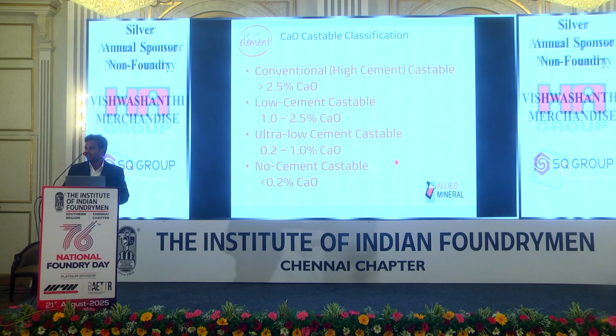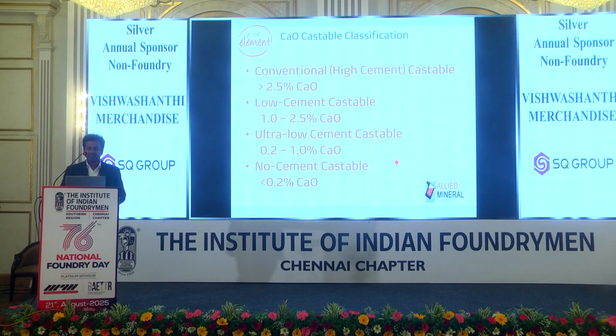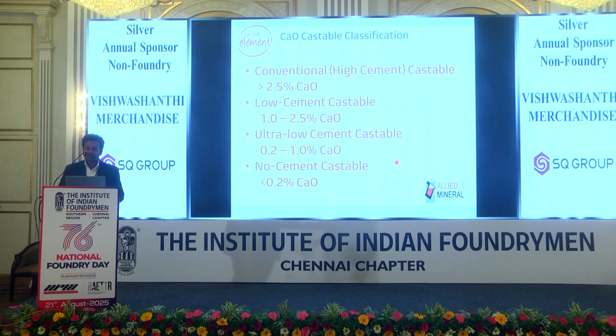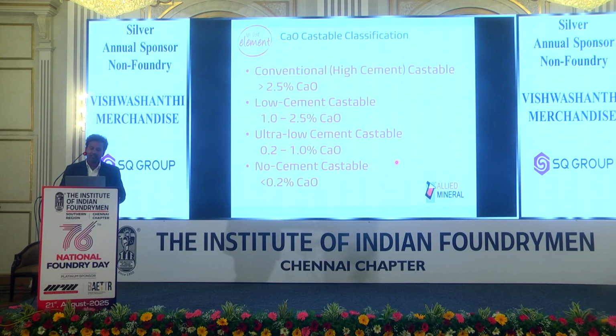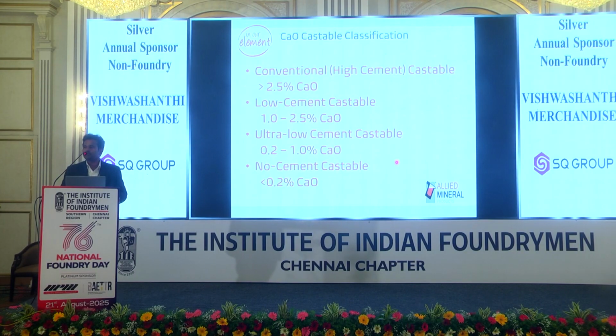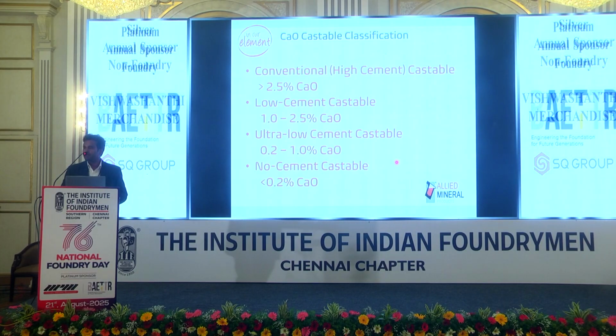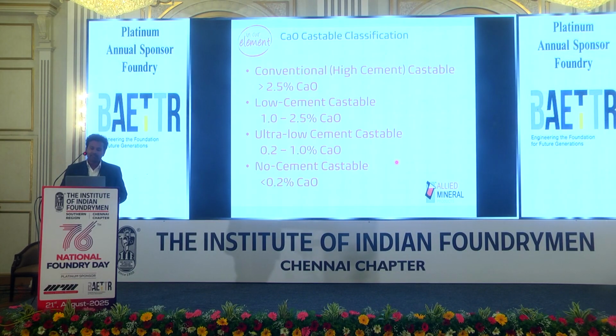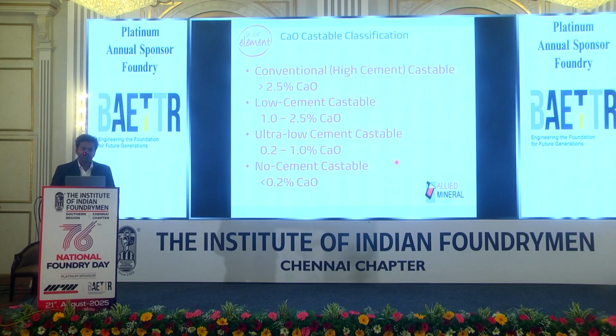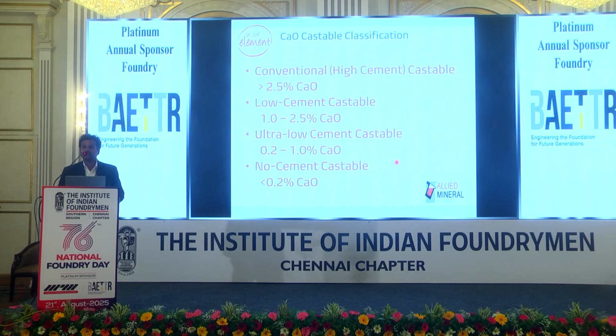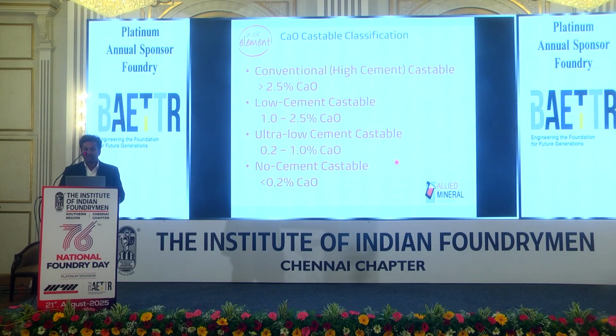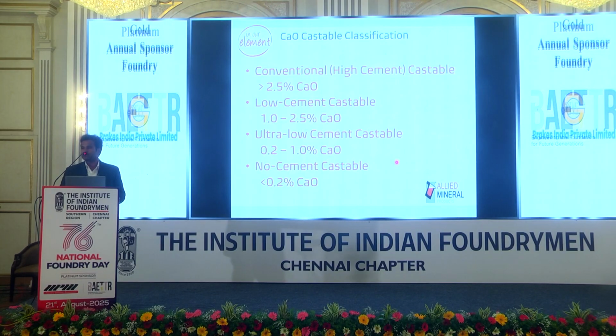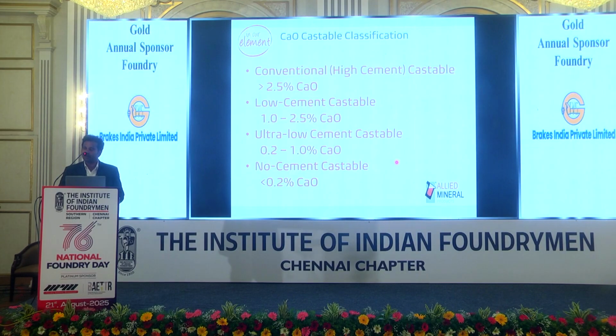So as I said earlier, there is no one product that suits all applications. The second is the low cement castable, which has very little, like 1 to 2.5% of calcium oxide. It takes very minimal water. And there is another category called ultra low cement castable, which is like 0.2 to 1% calcium oxide. And the final category is no cement castable, which is a completely different binding system like phosphate bonded or colloidal silica.